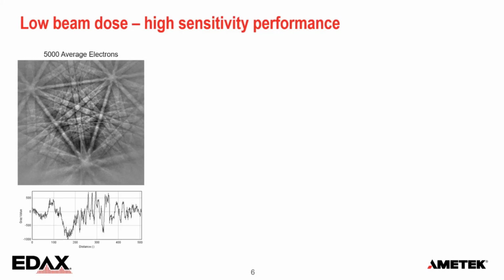So just a little example. This is a pattern collected with 5,000 electrons on average in each pixel. And you can see that the contrast in the middle is much higher than at the edges. And that is just the number of electrons hitting a certain part of the sensor. And if you look at the chart at the bottom, there's a lot of detail there. And that is really crystallographic detail that is coming from the diffraction.